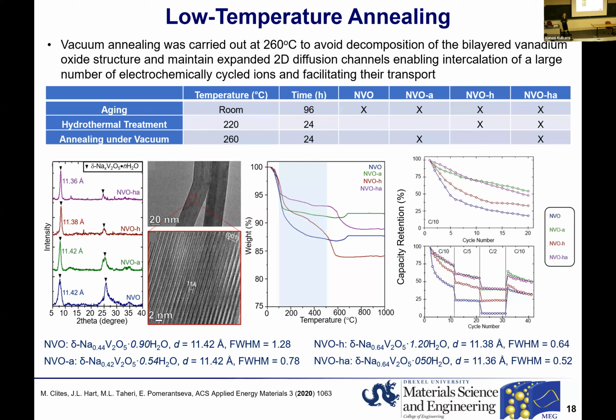So we've learned that through simple low temperature vacuum annealing, we can minimize this water content without phase transformation by annealing our materials at elevated temperatures. The highest that we could use is 260 C under vacuum. And while this performance is still not good, I promise to show you better electrochemistry today. What we found is that by annealing these materials at higher temperatures, we do see improvements.